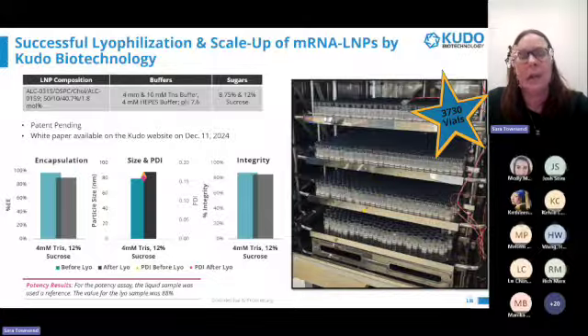Kudo Biotechnology has also experimented with the lyophilization of LNPs. For our formulations, we tried Tris and HEPES buffer with 8.75% and 12% sucrose. We had good success in these conditions and chose 4 millimolar with 12% sucrose for scale-up. As you can see from the data, we were able to scale up from an R&D freeze dryer to a pilot scale freeze dryer with no substantial loss in encapsulation or integrity and only minimal growth. We also tested post-formulation against the liquid sample, using the liquid sample as reference, and got 88%, which is a very acceptable value.